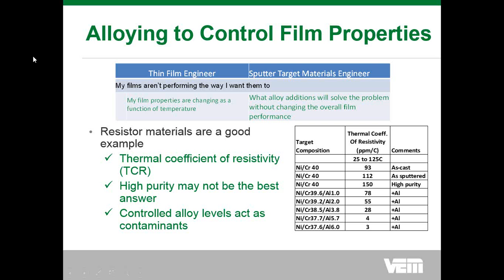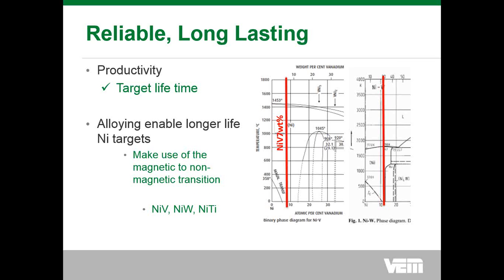And so now I've got a sputtering target that can produce a nickel film that etches very similar to a pure nickel film but is non-magnetic. Instead of being limited to a magnetic nickel target that may only be 3 millimeters thick, or maybe 1/8 of an inch, 0.125 inches thick, I can make nickel targets containing 7 weight percent vanadium as thick as 1/2 an inch or more, thereby allowing the thin film engineer to use this target in high volume manufacturing, minimizing the number of times they have to do a target change. Obviously, target changes reduce productivity.